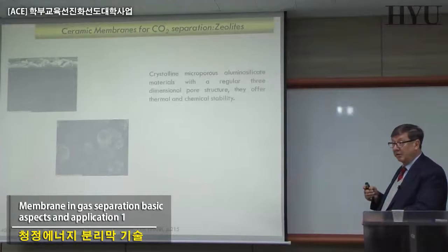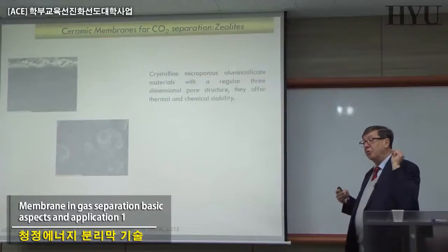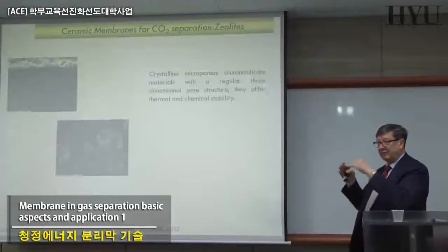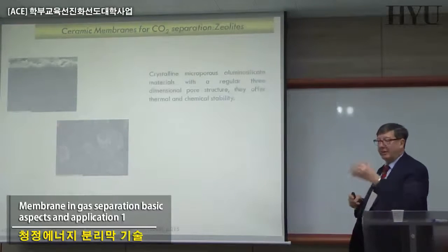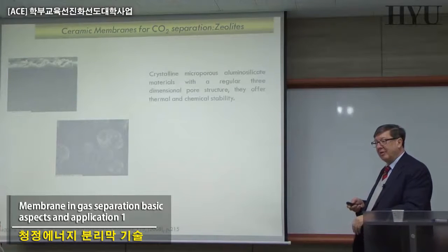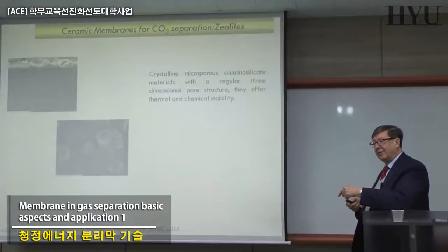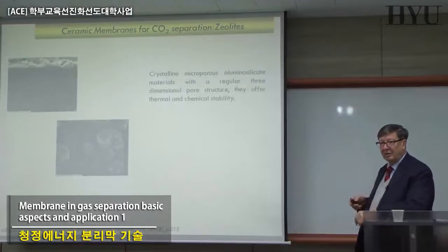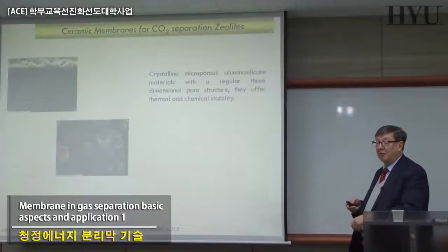You have to avoid that the gas, instead of going through the cages of this crystal, goes just between the matrix, the polymer in which you can fix your zeolites, and the zeolite itself. So the gas will penetrate not through the windows, but through the interface between the polymer and the zeolite.